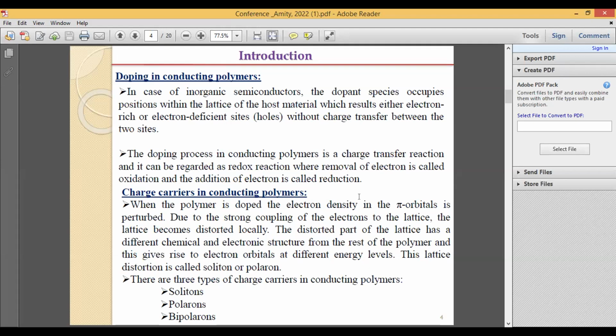And there are basically three types of quasi-particle carriers produced in conducting polymers, depending upon whether a degenerate energy state is there or not. If there is a degenerate energy state, then generally solitons are formed. For example, trans-polyacetylene is a conducting polymer having soliton carriers. In the other case, if there is no degenerate state, then at lower doping levels polarons are formed, and as the dopant concentration keeps increasing, bipolarons are formed.